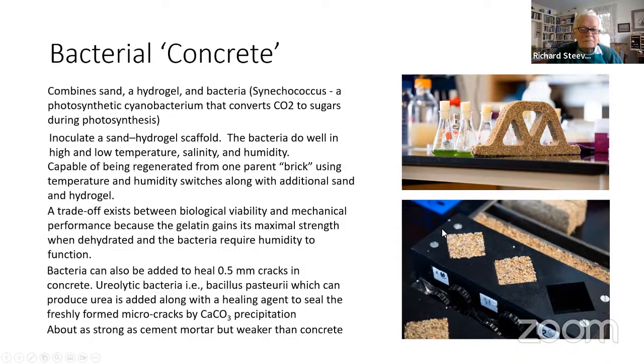And you can take a parent brick using temperature and humidity, and you can form another brick. So they sort of propagate on their own. That's cool. And so it turns out that there's a trade-off between the biological viability and mechanical performance, because the gelatin gains its maximal strength when it's dehydrated, but the bacteria require humidity to function. So there's a kind of sweet middle ground where this works best, or where these things grow best.